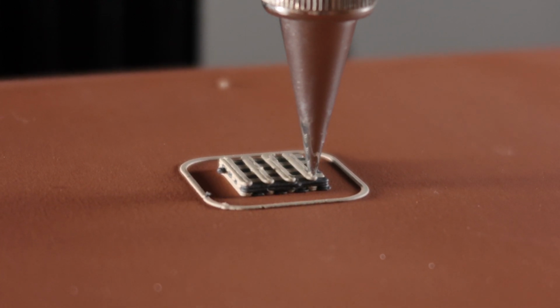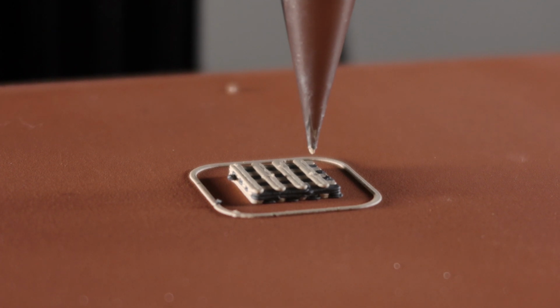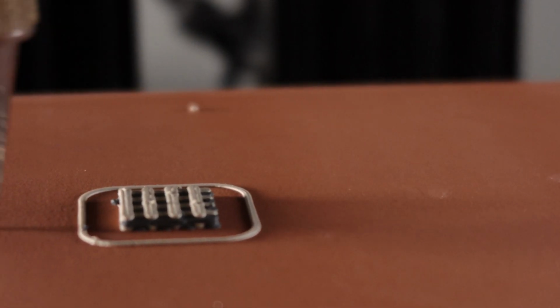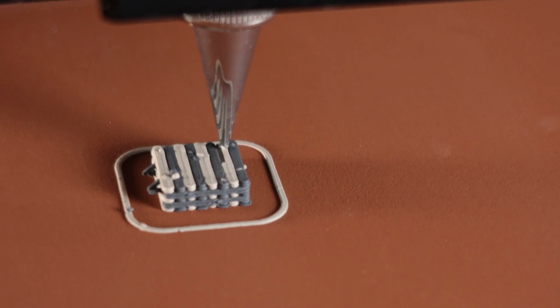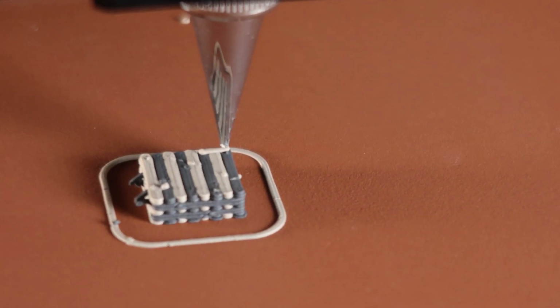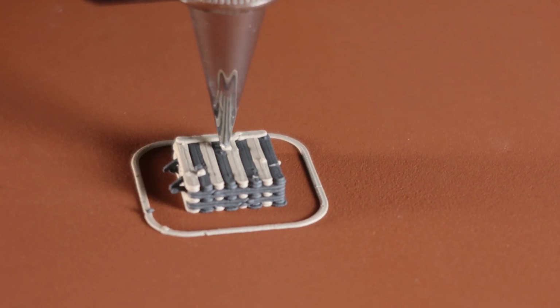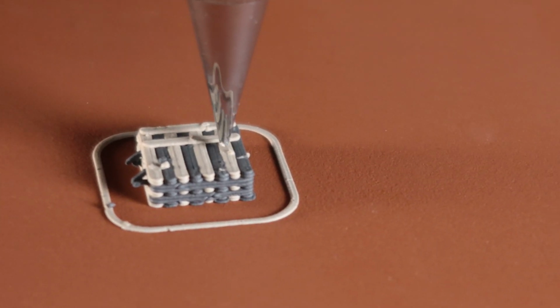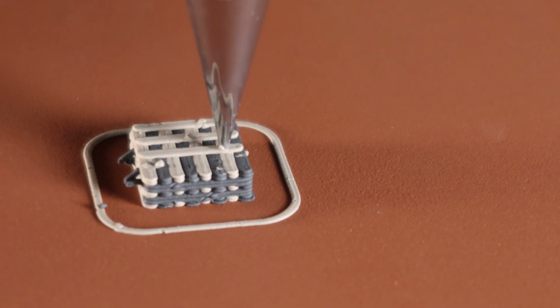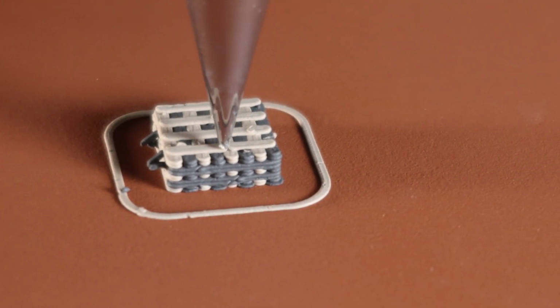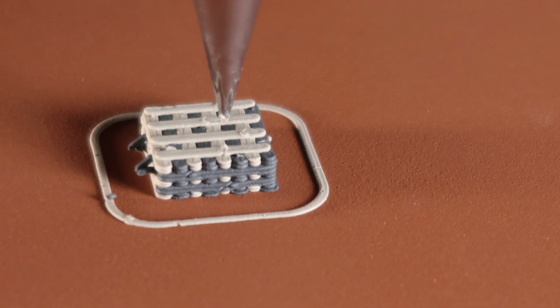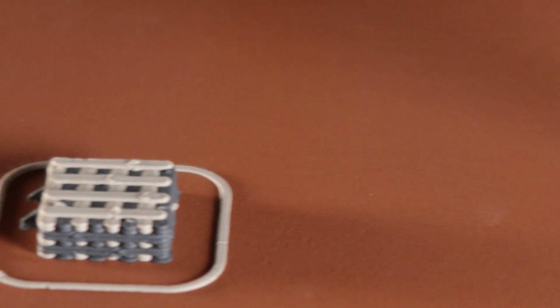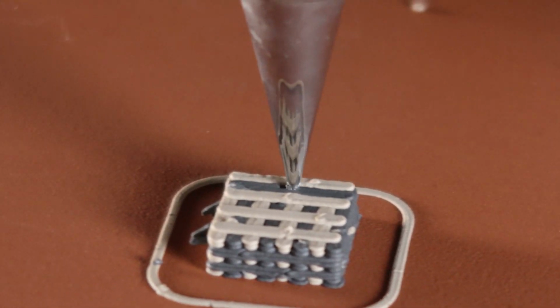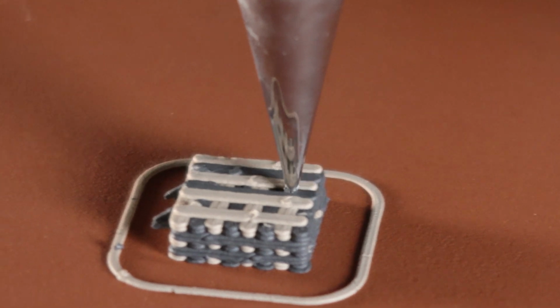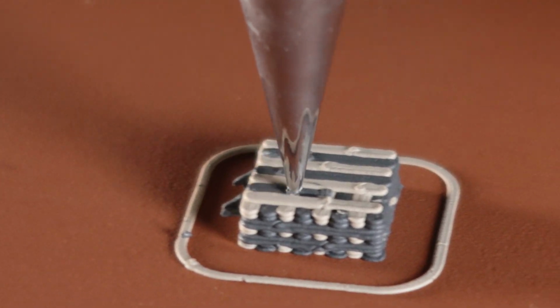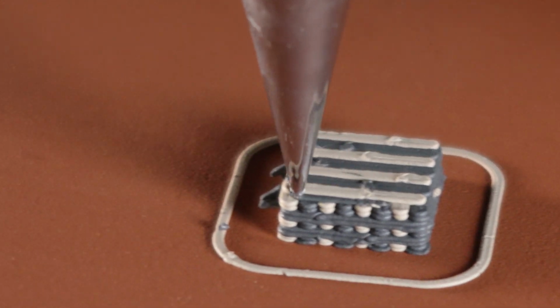And so one of the artifacts that you see is that there are some bits of extra dark clay that keep on getting snagged on the left-hand side of the print. And that, I think, is not a factor of software settings as much as it is a little bit of a difference in the two clay bodies. And so we used a white clay body and then added about 20% black ceramic stain to that white clay body to make the dark gray clay body. And so that addition of filler or color material did seem to change the behavior of the darker clay a little bit.